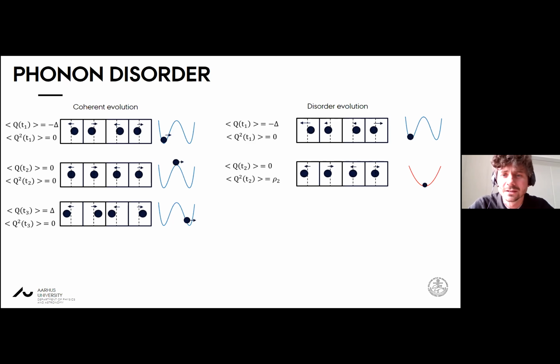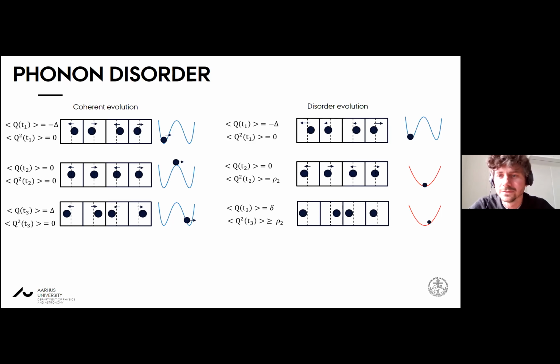We again reach, at a certain time, the state where there's zero net distortion in the system, but there is now a finite buildup of disorder measured through the mean squared displacements around that position. And if we let this system carry on evolving, it may overshoot to the other side of the potential, but it's not going to be trapped. And the disorder will potentially carry on growing.